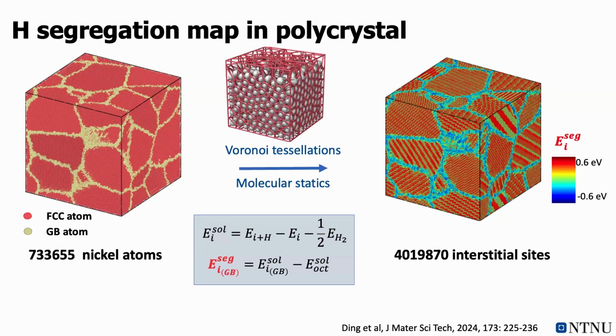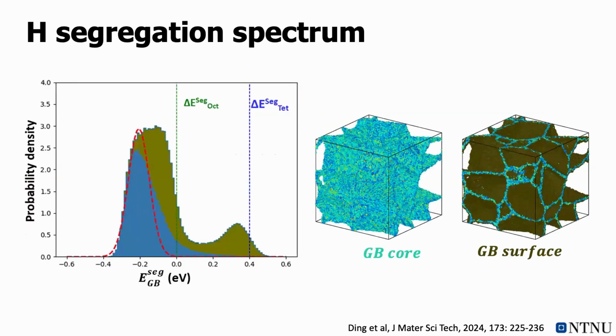So here we focus on the hydrogen-grain boundary interaction. We insert hydrogen into polycrystalline nickel with around 740,000 atoms. Then we have over 4 million interstitial sites in this polycrystalline structure. We focus on the segregation energy distribution of hydrogen occupying each possible trapping site, in the interstitial sites or in the grain boundary defect area, to see how the segregation energy is distributed. And here is the result.